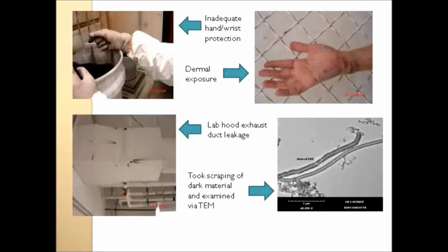Another finding that was somewhat serendipitous, because I happened to be looking up at the time, and the ductwork was painted white and carbon nanotubes are black. I spotted this dusting, if you will, at different points on the ventilation system, and noticed that that might indicate that there was some kind of leak. And you can see by the plume that it was blowing out instead of being pulled in to the duct. So this was a positively pressured duct that was handling the fume hood that was supposed to contain the carbon nanotubes. And I took a scraping of that and sprinkled it onto a mixed cellulose ester filter and looked at it under TEM, and lo and behold, there are carbon nanotubes. And that was something that could have easily been missed if somebody, for lack of a better word, didn't have a trained eye to look for something like that. So these are things that pop up over and over again.